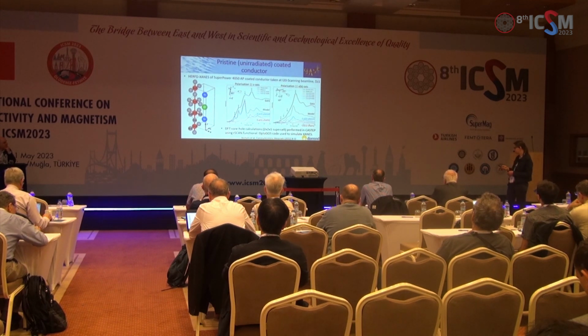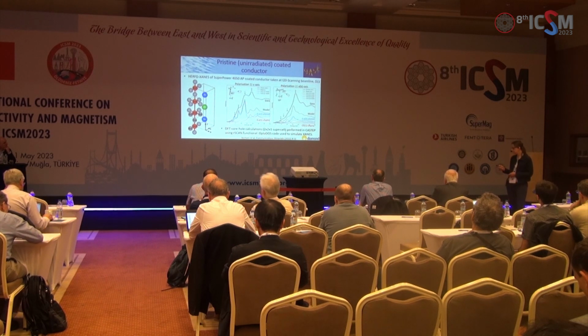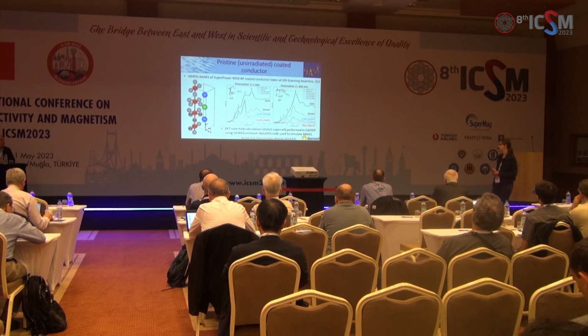And what you can see first of all is that we can split our model into components that are coming from the copper in the planes of the structure, which are these planes in the REBCO structure, compared to copper that are in the chains along here. So we can see straight away that these features along the rising edge are coming from the copper 2 atoms in the structure, the copper planes. If we look at this one, a lot of these features are coming from the chains, but this peak has a large contribution from the coppers in the plane again.